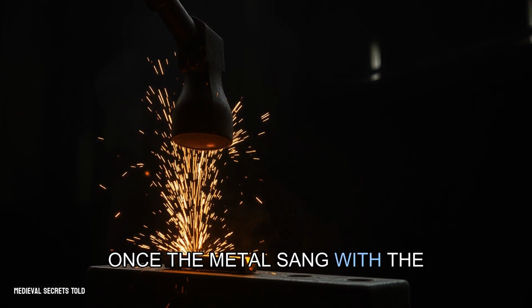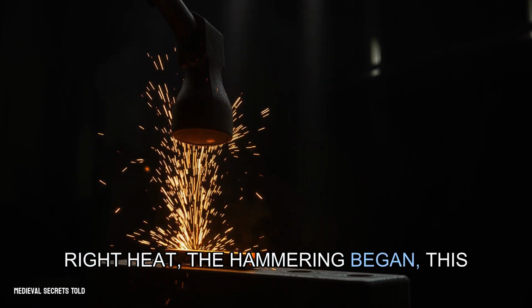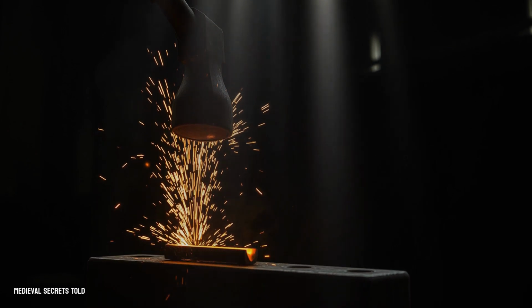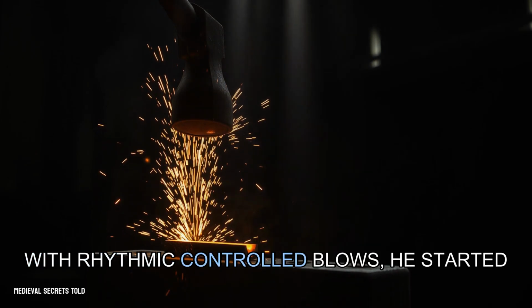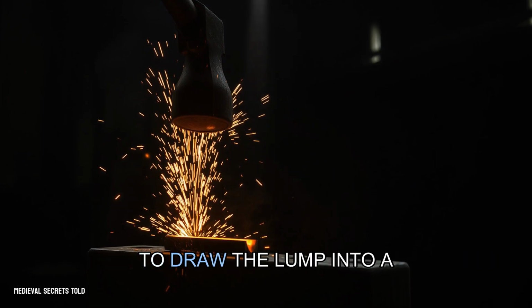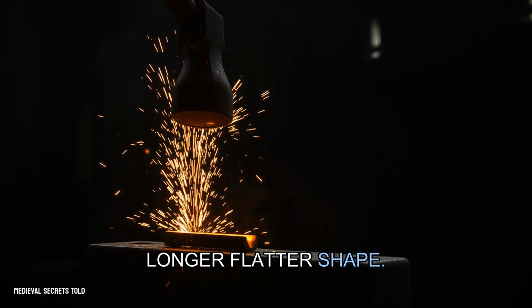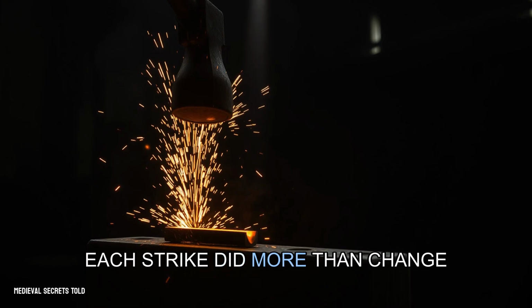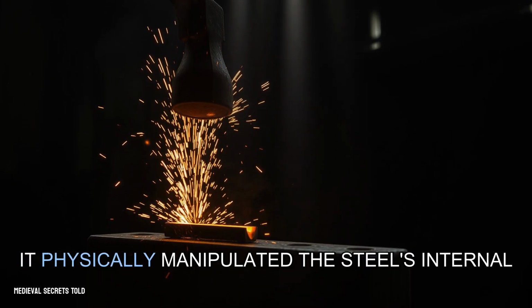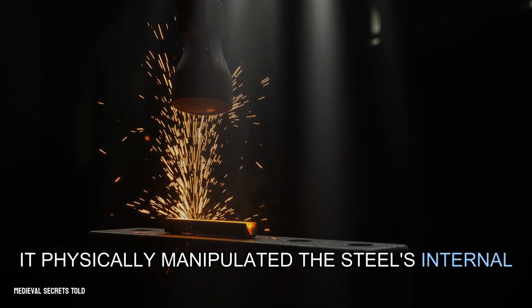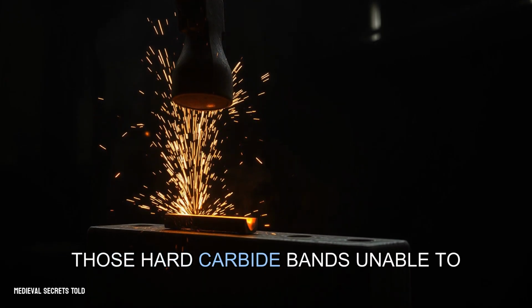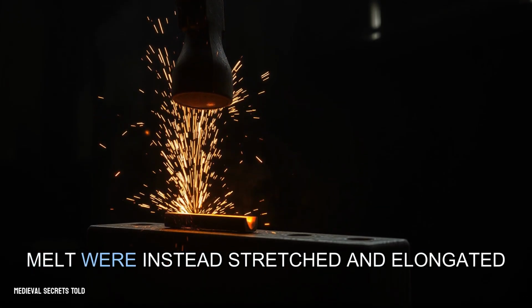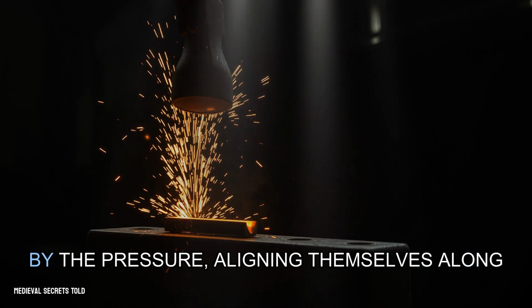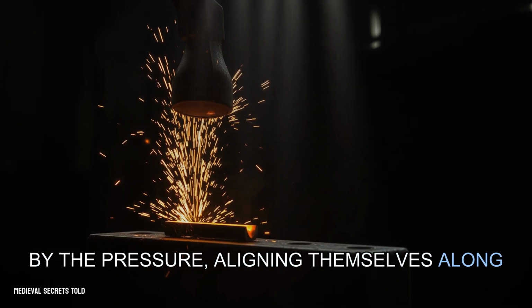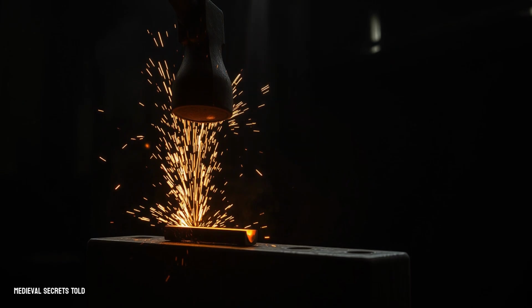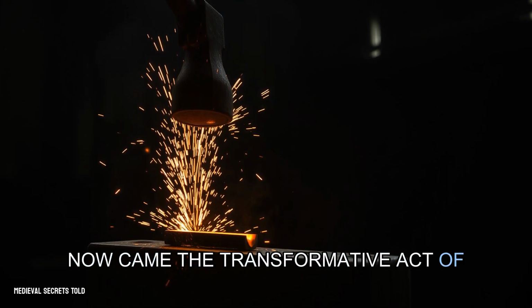Once the metal sang with the right heat, the hammering began. This was not brute force, but a conversation. With rhythmic, controlled blows, he started to draw the lump into a longer, flatter shape. Each strike did more than change the form. It physically manipulated the steel's internal world. Those hard carbide bands, unable to melt, were instead stretched and elongated by the pressure, aligning themselves along the length of the emerging blade.